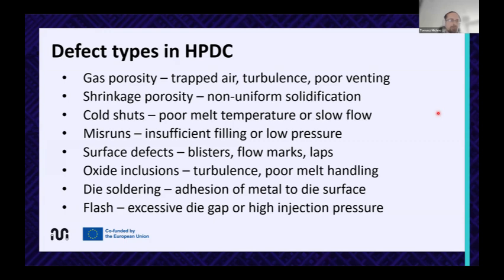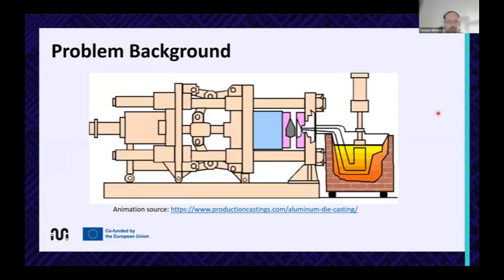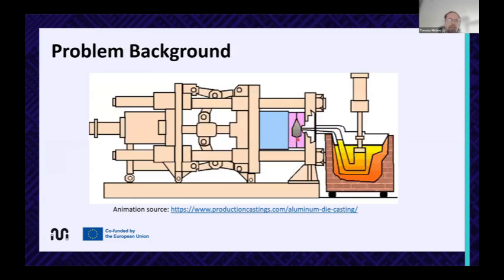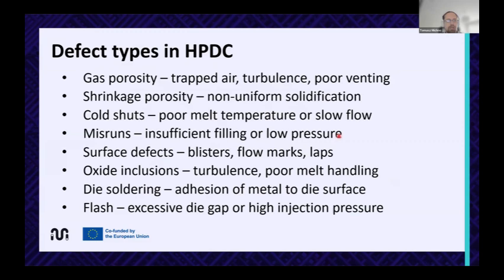There is also shrinkage porosity. Because of different types of solidifying and the setup which we are using, as in this animation, there are different areas of the mold which can cool down a bit differently than the others. So this part is not always cooling down in the same way in all areas. This may also cause some porosity, so also some bubbles inside, because of different shrinkage regions when the part